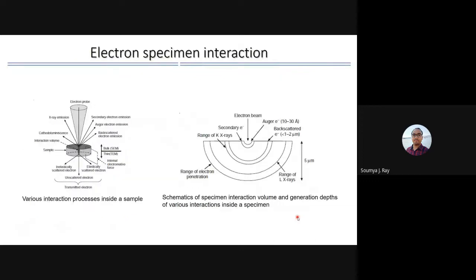So let us try to see what type of interaction happens here. Let's say this is the electron beam or electron probe that is coming up here, and then it interacts. There will be different types of electrons. The first is secondary electrons. Then there will be Auger electrons and backscattered electrons, and then there will be X-ray emission. Each of these types will have information about different parts of the sample. For example, Auger electrons are sensitive to a thickness of 10 to 30 angstrom. Backscattered electrons can provide you information typically at the length scale of 1 to 2 micrometer. Secondary electrons are also sensitive to very small length scales.